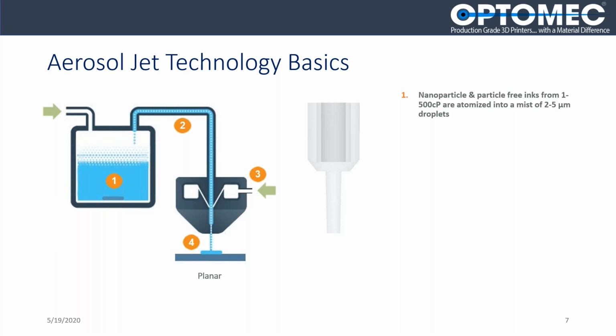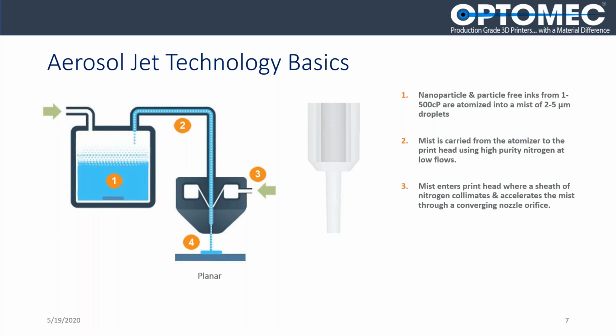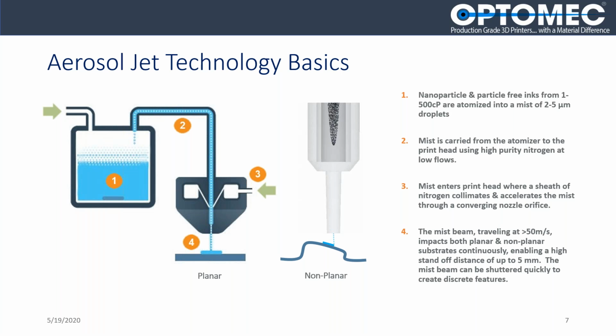And those materials are atomized into a dense aerosol. We then use a high purity gas, nitrogen in most cases, to transport the aerosol down to the print head, where we add a sheath gas, which collimates and accelerates the aerosol beam through the nozzle and down onto the substrate. And as you can see in this short CFD simulation of how that sheath is introduced, you can see that the mist is moving slower here and obviously accelerating as it's jetted onto the part.